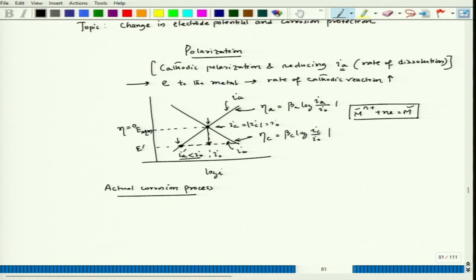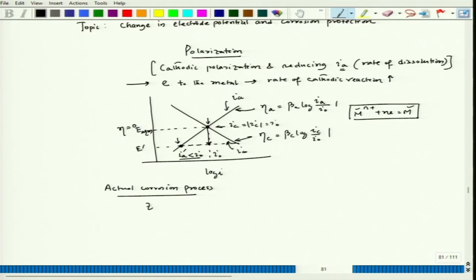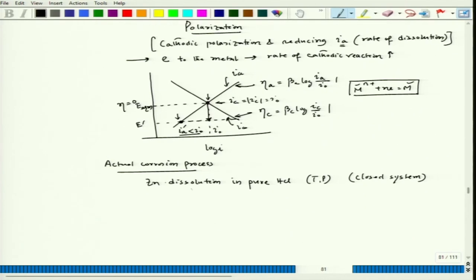Now, actual corrosion process, it actually handles minimum two processes and those two processes will be handling two different species. Let us say, see this zinc dissolution in pure HCl, let us say temperature pressure fixed. And let us say for the time being, let us consider this is a closed system. So, now if we allow this particular process to happen, we immediately will see on top of zinc, hydrogen bubble will form. And then zinc gradually goes into the solution. So, we will have this reaction.